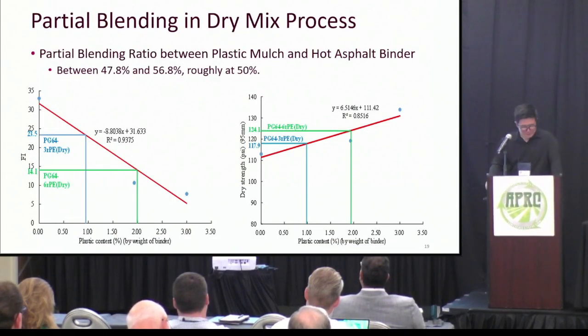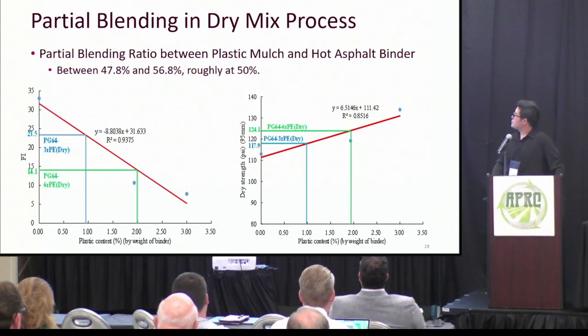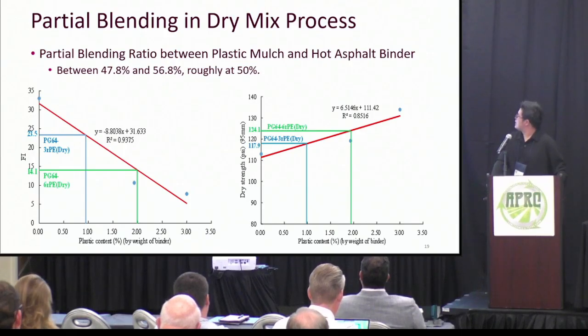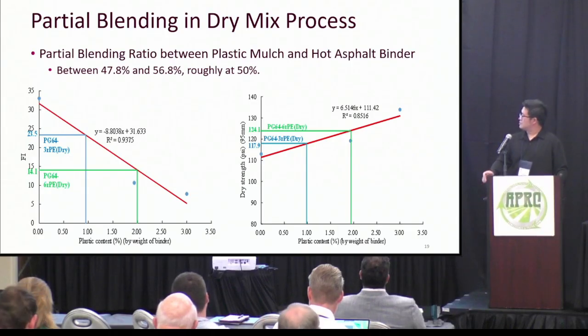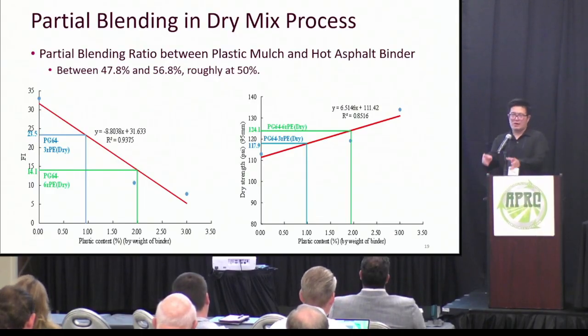So you may be wondering, when you use the dry mixing method, how much plastic blends into the asphalt. So we used some results from the cracking test to estimate the partial blending ratio between the plastic mulch and the hot asphalt binder. The results show that it's between 47% to 56%. So roughly speaking, 50% of the plastic melts into the asphalt.